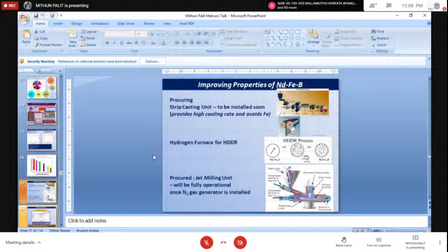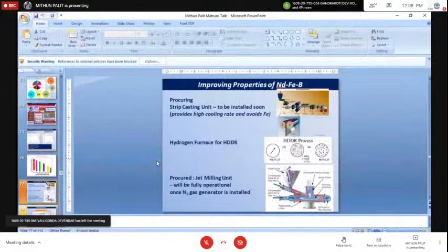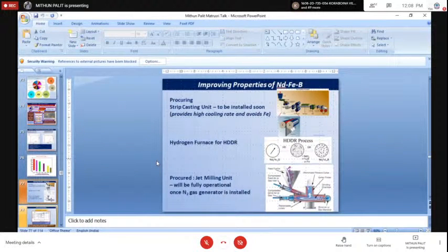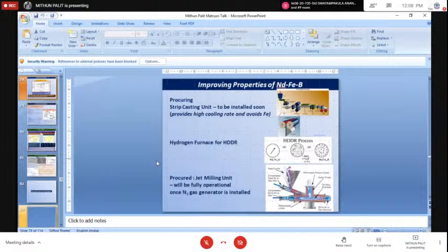And now hydrogen is also being used to process this NdFeB. Why is hydrogen used? Because the hydrogen will actually go into the Nd-rich phases that I showed, the shielding phases. So hydrogen goes into those phases, and by doing that, it will make that phase very brittle, and accordingly the 2-14-B particles will be standalone and they will break out of it. So you now have nice 2-14-B particles. You can orient them magnetically very nicely and get a very good property.